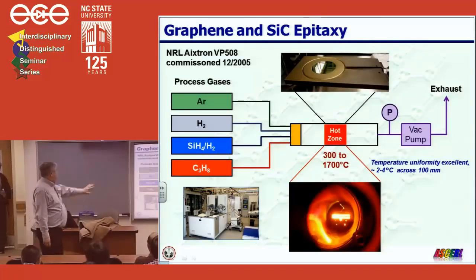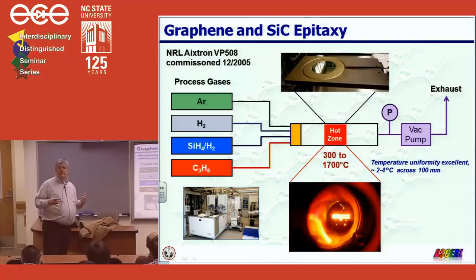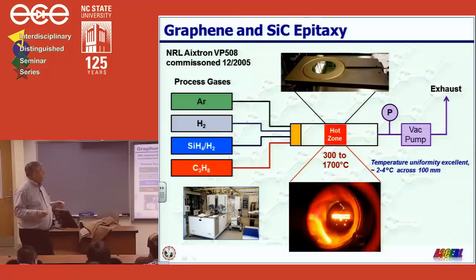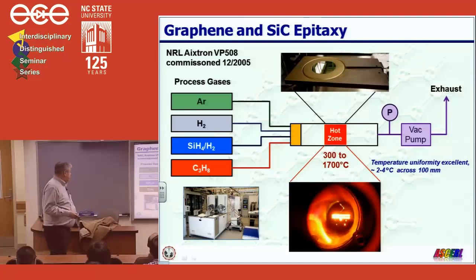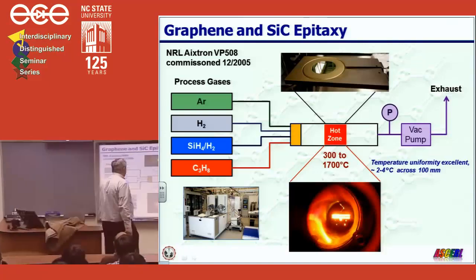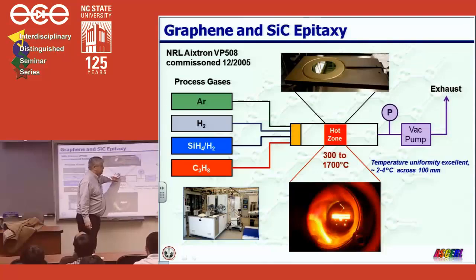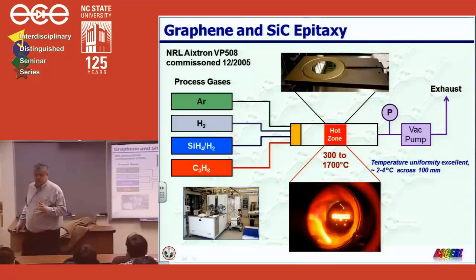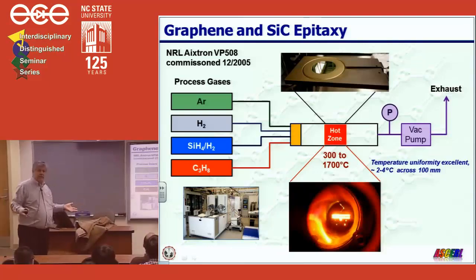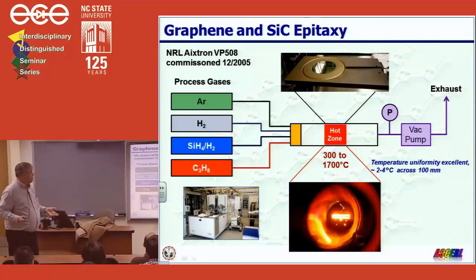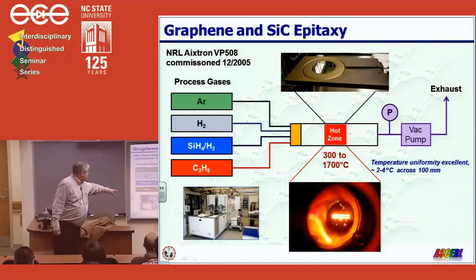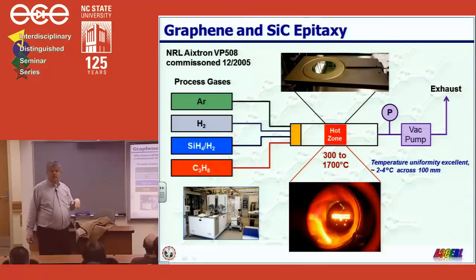Okay, the way we do it, it's a standard process. We have a CVD reactor. It's the same type of reactor that you would grow silicon in or silicon carbide. It happens to operate at slightly elevated temperatures. We do the process at about 1600 degrees. But the wonderful thing about our reactor is the hot zone has an extremely uniform temperature profile. And since it's a sublimation process, it's all thermally driven. So that becomes very good if you want to make uniform layers of graphene. And so that's one of the reasons for our level of success. The lower left picture is a picture of the reactor, and the schematic shows the various processing gases we can put into the hot zone.